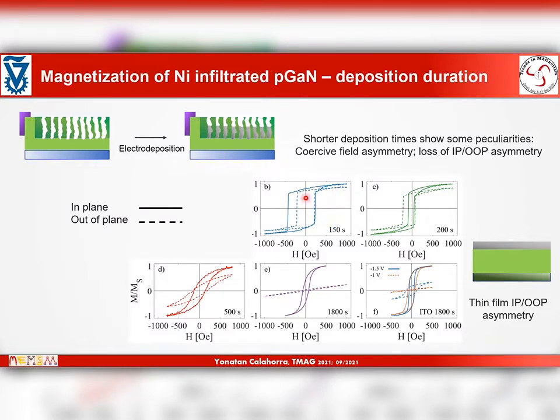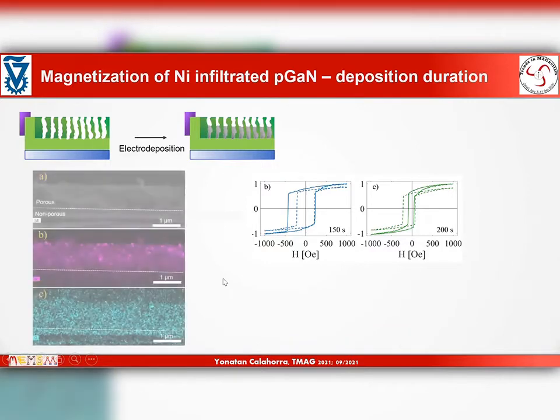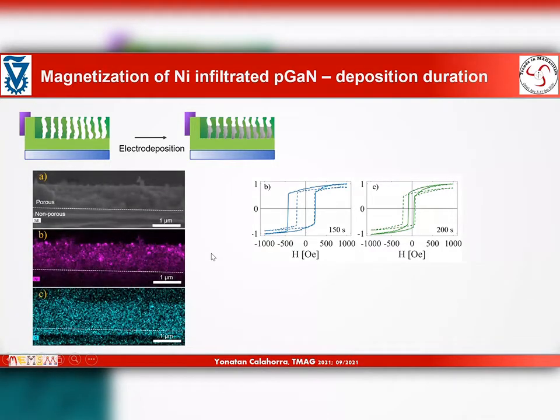So the in-plane, out-of-plane asymmetry is almost lost. And we also see some peculiarities in the coercivity, asymmetry in coercivity, and all these behaviors die out and transfer to a more thin film-like behavior when the electrodeposition is at longer durations, moving on to fully thin film for thicker films. So let's focus on these two shortest or shorter deposition times.